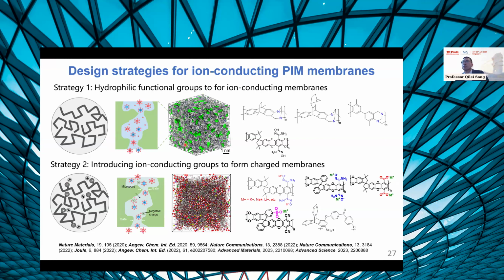I want to quickly go through some of the design strategy. Firstly, we developed this hydrophilic functional group for ion conductive membranes. You can see that some of these membranes, PIM polymers like Tröger's base, have hydrophilic functionality. So when we develop these materials into membranes, when they absorb water or electrolyte, they become ion conductive membranes. Another strategy is incorporating ion conductive groups into the polymers to form charged membranes. We have developed several different functional groups, including the amidoxime, the carboxylic acid, and the sulfonate groups.